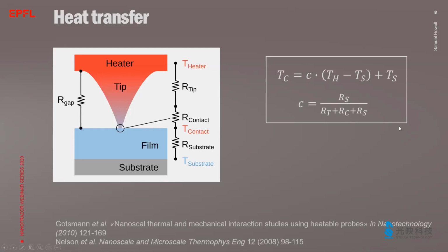So on the one hand, higher tip resistance and higher contact resistance decrease the heating efficiency. On the other hand, a higher substrate thermal resistance increases the heating efficiency and hence the contact temperature. So in case of a 4-inch silicon wafer, we have seen that the substrate is huge in comparison to the heated tip and acts as an efficient heat sink. So in order to heat a thin film to a temperature larger than the substrate, the film material should be a good thermal insulator. Luckily, this is the case for most polymers.